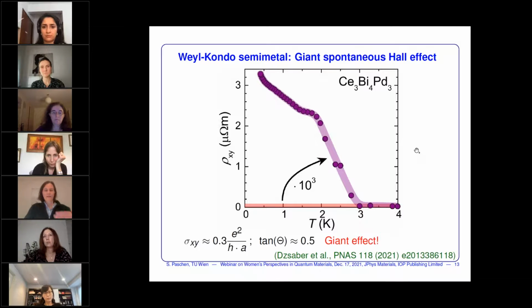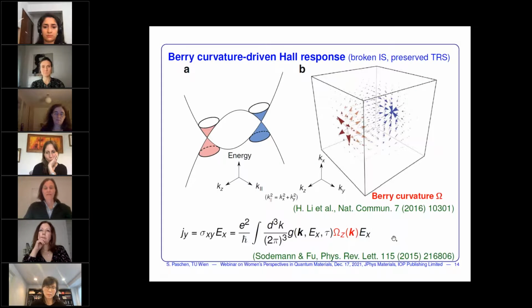So what is that? You take your sample, you feed a current through, like in a normal resistivity measurement, but you don't do anything else. And you measure the transverse voltage, and it is there. Usually you need to apply a magnetic field to the system to have that, but we don't do that. And also the material intrinsically in itself is totally non-magnetic. So that is a very amazing effect, that you sort of get deviation of carriers out of nothing, apparently, and it's a giant effect. In fact, people have an idea where it comes from, and there is a theory that predicts such an effect.